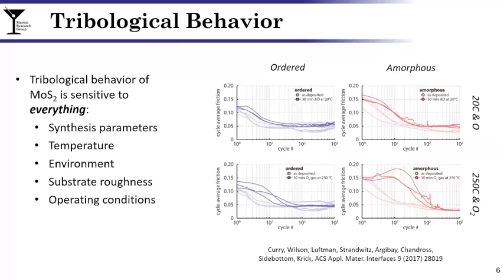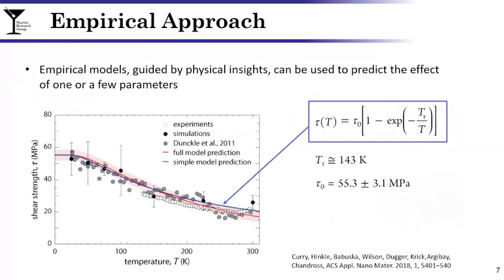One approach to capturing these complex interrelationships is empirical modeling. I'm showing you here just one example of shear strength or frictional resistance as a function of temperature, where the experimental data was fit to the equation shown on the right. The fit parameters in this case were informed by atomistic simulations, but nonetheless, this is a good example of taking experimental data and fitting it such that one can use the fit equations to guide design. And this approach is widely used and is very appropriate for one parameter or perhaps even a few.